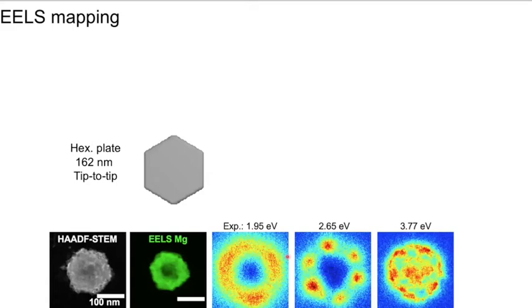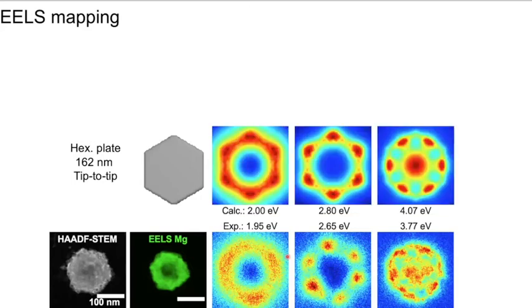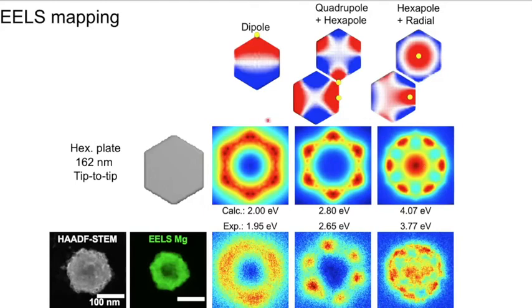But thankfully I have wonderful collaborators here in Cambridge, and John Biggins is one of them. He's been able to do numerical calculations on this to help my group understand what the excitation actually is that we're probing. The first thing he does is simulate the EELS response and make sure that we're thinking the same thing. And indeed the simulated EELS match really well, both in distribution and in energy. And then we can look at the field distribution, the blue and red, as we call it. This is basically positive and negative, if you want. And what we can see is that, of course, the first excitation in these particles is a dipole. And it looks like a donut indeed, because anywhere you go around, you are going to excite a dipole.